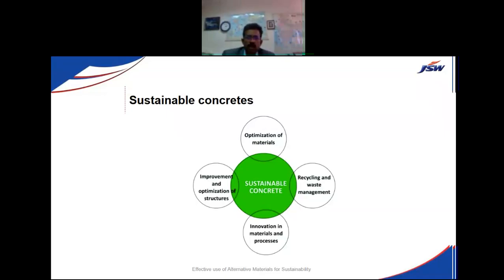I'll tell you. People are using slag sand or copper slag sand. Then they're using GGBS or fly ash. They're going for ultrafine material: metakaolin, microsilica, ultrafine fly ash, ultrafine GGBS. Okay, so there are four products based on the requirement. Then we are using fibers. In terms of admixtures, we are using waterproofing admixture, PC-based admixture. Okay, so already how many products have we put? More than 7 to 8 products, to modify the properties of concrete, to modify the flowability, and to improve the strength and durability performance.